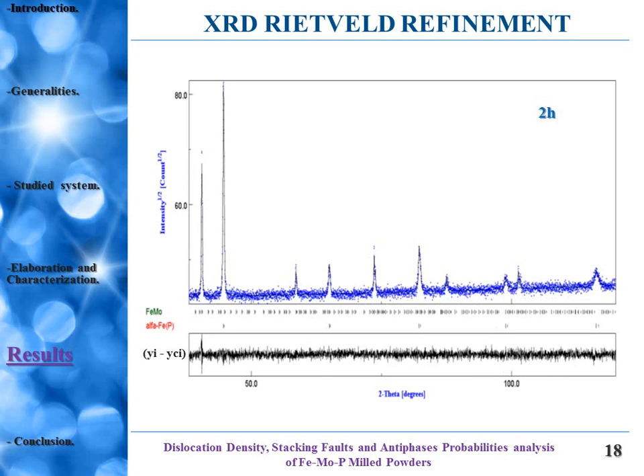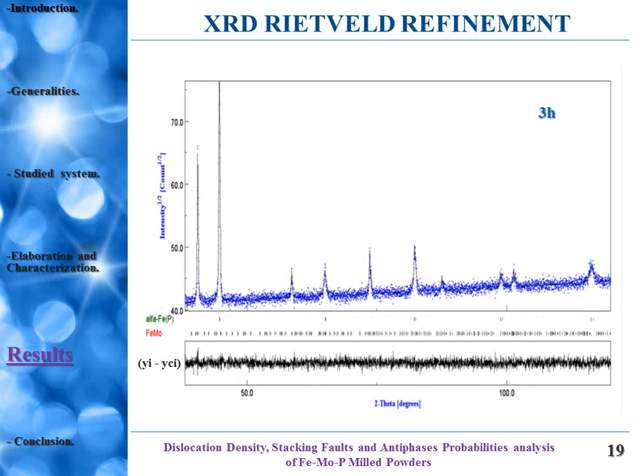After 2 hours of mechanical milling, no new phases had formed, only the iron molybdenum phase and the solid solution. After 3 hours of continuous mechanical milling of the mixture, no new phases appeared, but this arrangement is different from 1 hour and 2 hours of milling. The only stable phases obtained from 1 to 3 hours of milling are iron molybdenum and iron phosphorus solid solution with different structural and microstructural parameters.